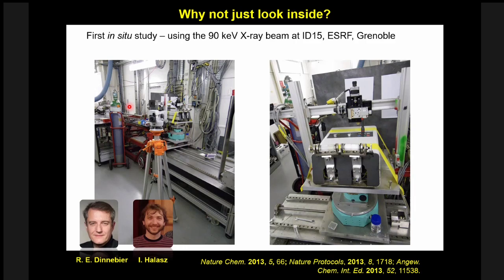We also have observed, and I was very shocked by this, that in some cases roughly 30 or 40% of the reaction mixture is amorphous. Compare that to actually doing the milling, taking the sample out and measuring separately. In such an experiment, we see maybe up to 5 or 6% amorphous phase. So this tells us that during milling there is a lot of amorphous, non-crystalline, I like to call it active phase in there. And the moment your milling stops, it looks like this phase just relaxes so quickly by crystallization, you don't know it was there. So we are seeing some interesting new mechanistic insight. It's not only just the kinetics, but the composition of the mixture that we are elucidating. That's really cool.